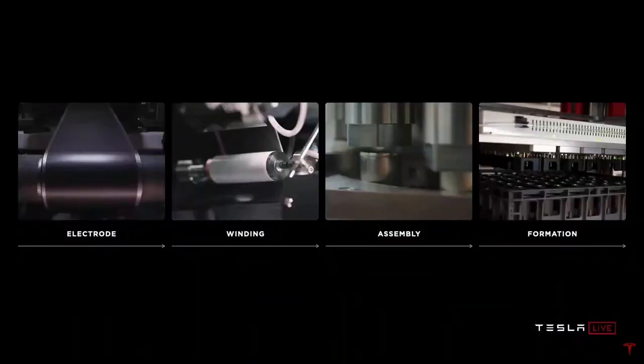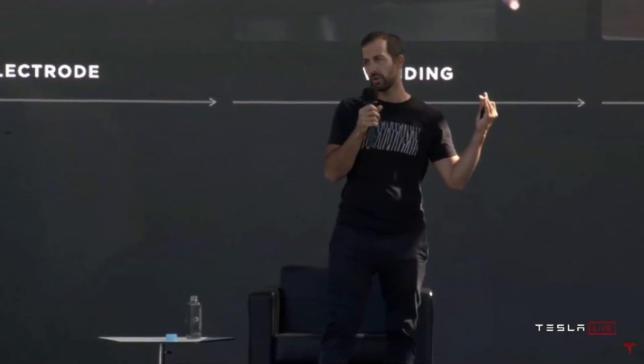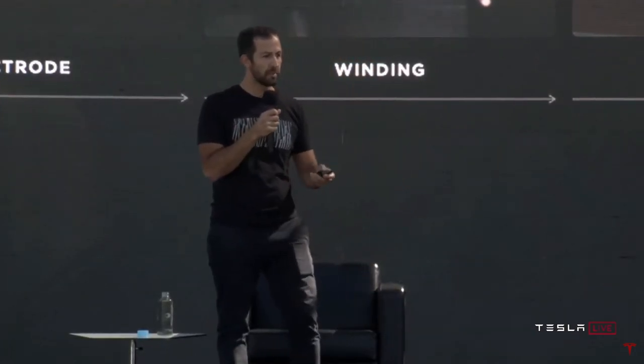And let's talk a little bit about what's in a cell factory. First, there's an electrode process where the active materials are coated into films onto foils. Then those coated foils are wound in the winding process we just talked about, where if you do have tabs, you have to start and stop a lot. Then the jelly roll is assembled into the can, sealed, filled with electrolyte, and then sent to formation, where the cell is charged for the first time, and where the electrochemistry is set and the quality of the cell is verified. And we set out at every step of this process to take that inspiration we just showed and think about how we make those processes fundamentally better and more scalable.